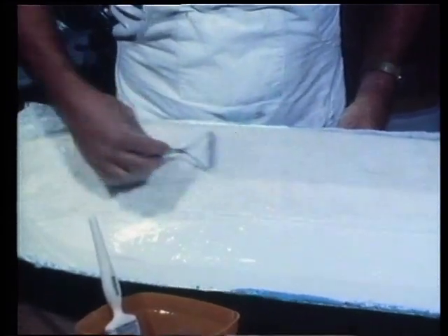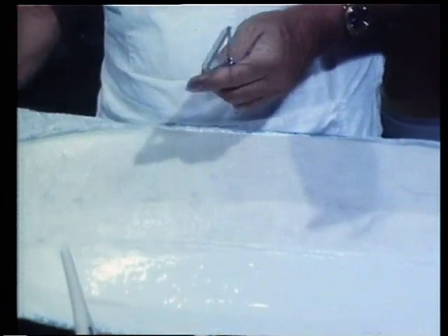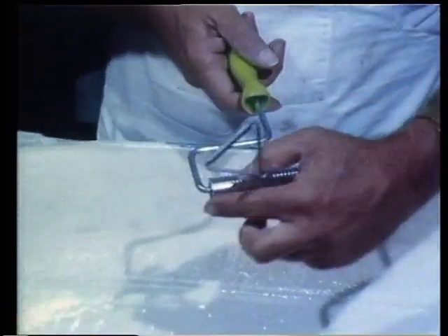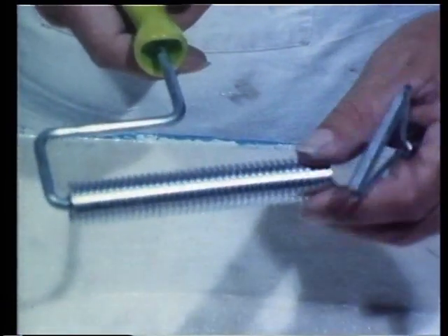Using the compressor roller, which with this larger compressor roller you can see what it is. It's effectively a series of flat washers which are on a roller, on an axle there. I have to use the small one on this boat. But that presses the strands of fiberglass down against the back of the gel coat, and in the process squeezes all the resin and the air up through it and consolidates the laminate. Now it's most important that all air bubbles be completely removed from the fiberglass laminate. So you go over it very thoroughly with the roller.